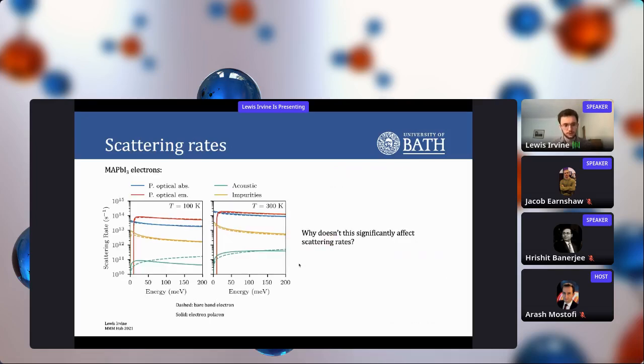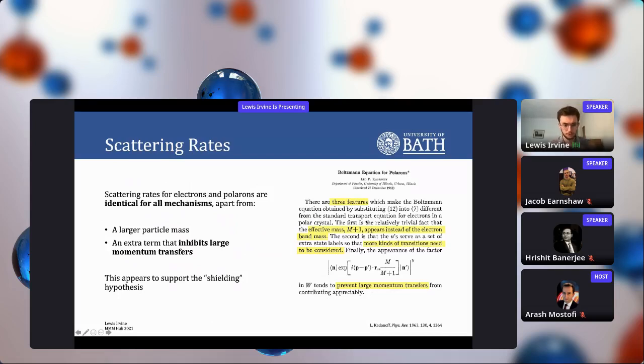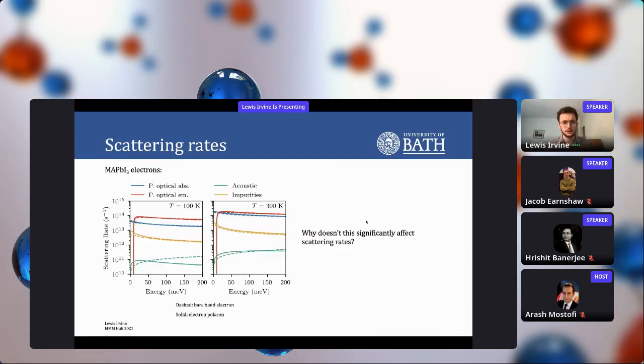But then when we run the numbers, we actually get very similar scattering rates for electrons and polarons, which are the dashed and whole lines here, for all of our scattering mechanisms, apart from acoustic. And even for acoustic, although you get very different scattering rates at low temperatures, when you go up to room temperature, the rates tend to converge again. So the question is, we derive these rates that look a bit different. Why don't they actually matter all that much?